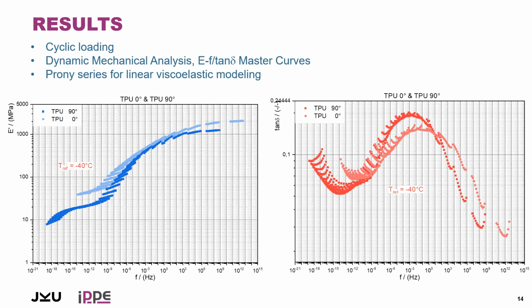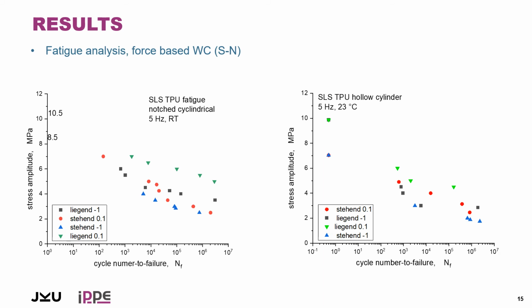Then finally, using the same specimen and same test setup, we performed fatigue tests, very similar to the conventional fatigue test, at two stress ratios, -1 and 0.1. And also for both printing orientations, does it mean the parallel and the perpendicular? And you see these results for both the notched specimens and also for the hollow cylindrical unnotched specimens at 5 Hertz. And as you see, there is a clear ranking between the materials.